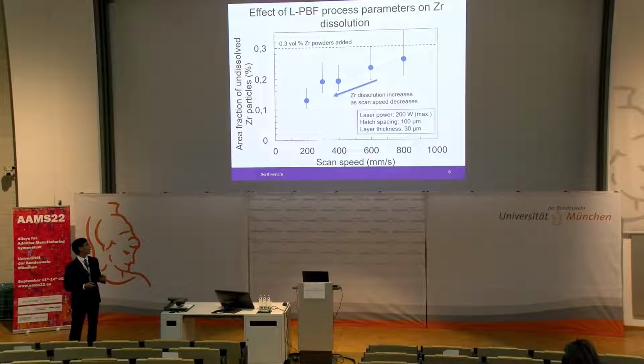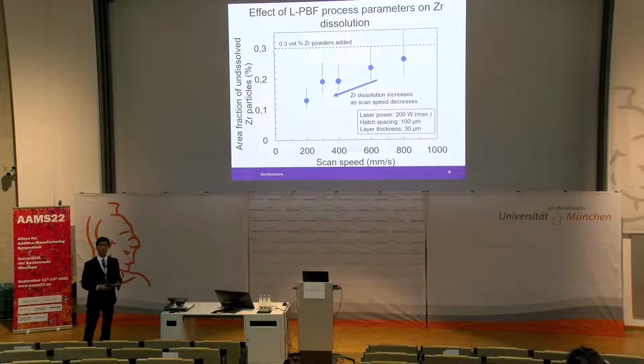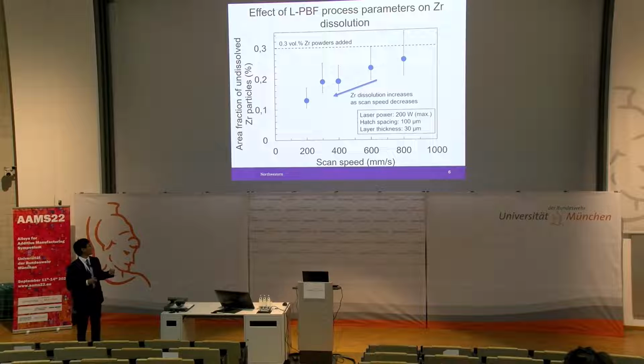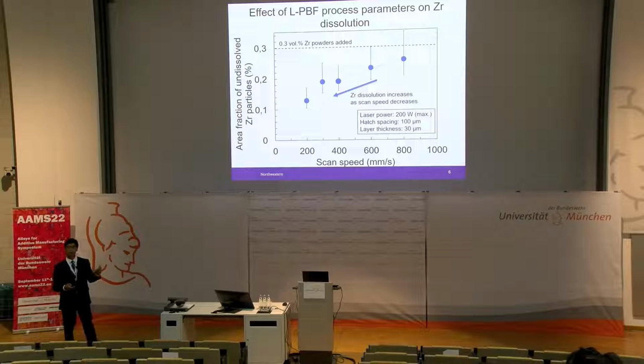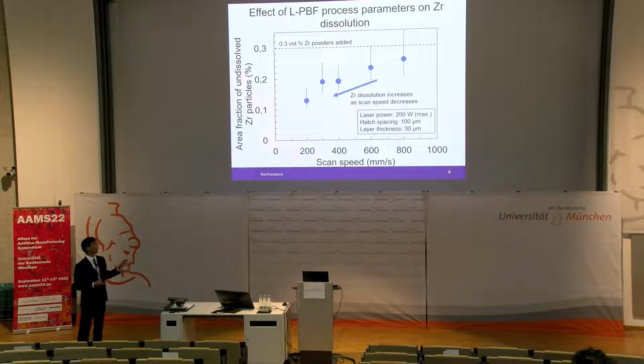What we see is that as the scan speed decreases, the area fraction of these particles also decreases, indicating that the amount of zirconium dissolved is increasing. This is quite expected, since as we decrease the scan speed, we're increasing our volumetric energy density. We're also increasing the amount of time that the zirconium particle can spend within the melt pool. One might think that in theory, we could go to even lower scan speed and dissolve more zirconium. However, in practice, this severely compromises the integrity of the parts that we build. So we can't really go any lower than this.